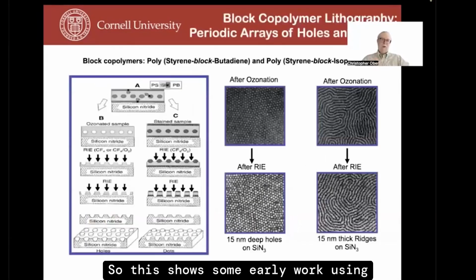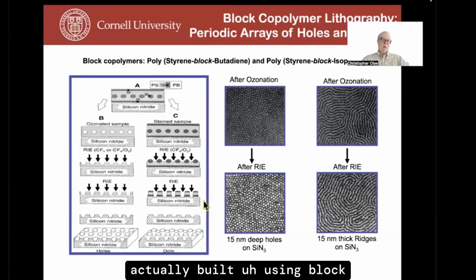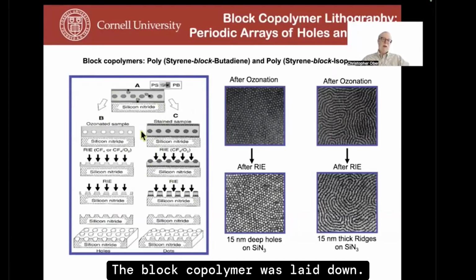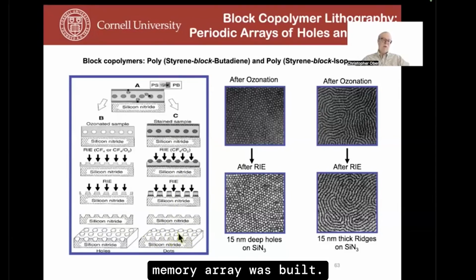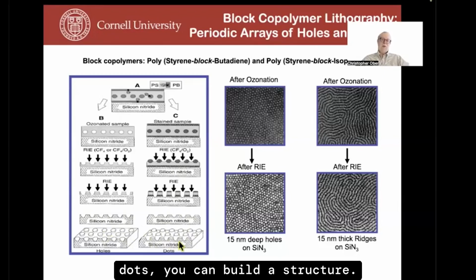So this shows some early work using styrene butadiene and styrene isoprene, where a device was actually built using block copolymer patterning. The block copolymer was laid down. The reactive ion etching was used to eat up the softer part of the photoresist and leave the harder part of this block copolymer photoresist behind. And then through reactive ion etching into silicon nitride, pillars were made. And so a quantum dot memory array was built. So you can make holes, you can make dots, you can build a structure.